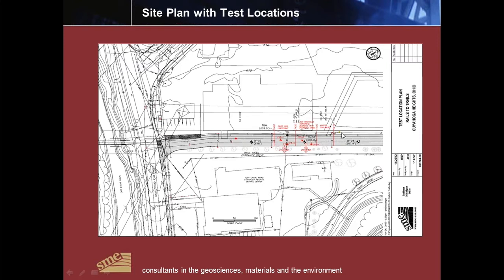This plan view shows our actual test section areas. This first section here is the standard ODOT 304 limestone. The second section here is the recycled concrete foundry sand aggregate, and we had a third section with a different material in it. As part of the original study, there were soil borings conducted along the railroad right-of-way, and in addition to that, there were several static cone penetration tests probed into the subgrade to give us a better understanding of the relationship of the subgrade to the natural subgrade. As part of the project, we also installed two lysimeters located under each of the primary pavement sections, called lysimeter A and lysimeter B, and we collected groundwater flow through the base course and did analytical testing on those water samples.